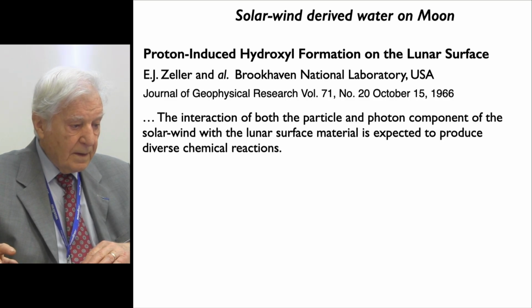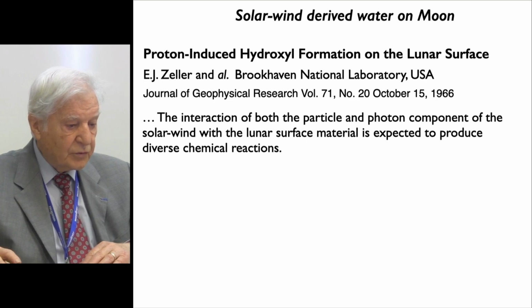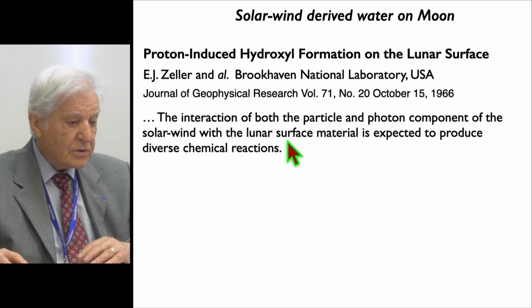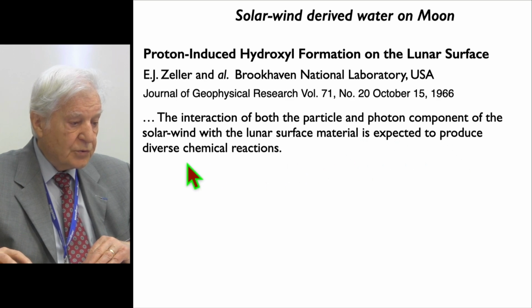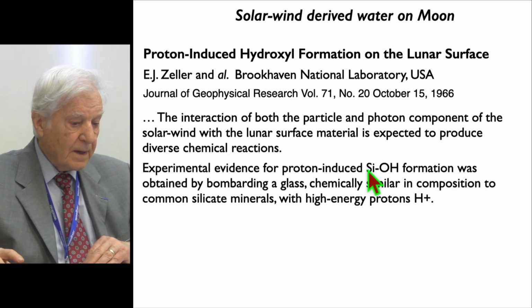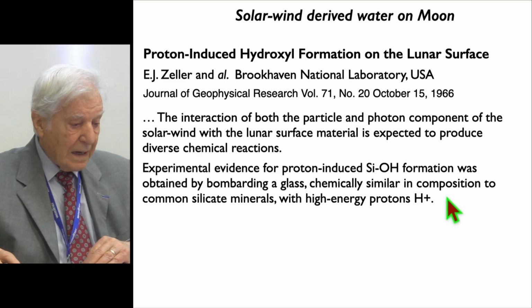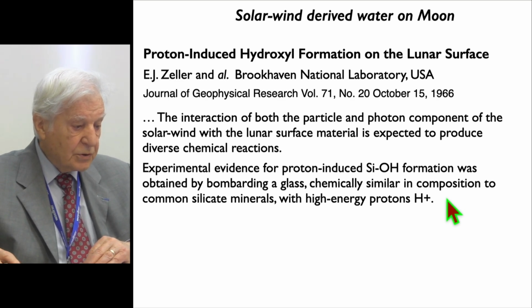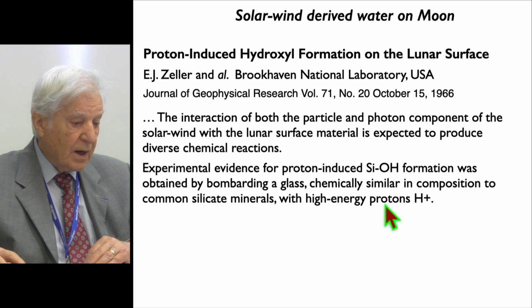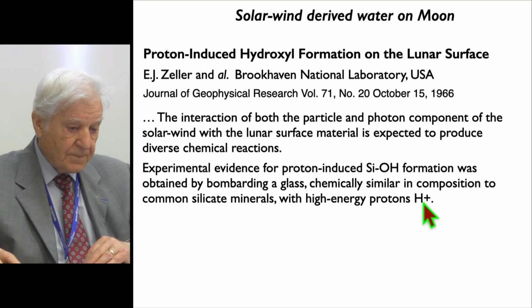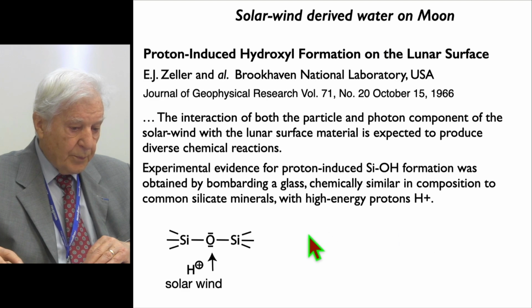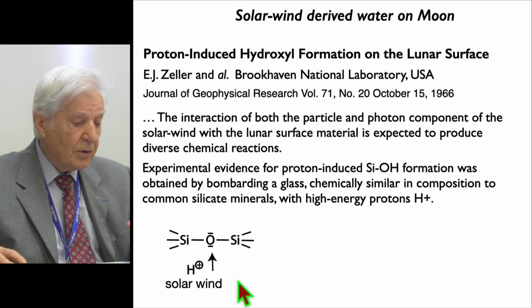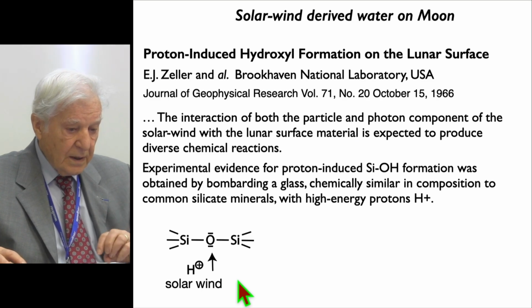I read. The interaction of both the particle and photon component of the solar wind with the lunar surface material is expected to produce diverse chemical reactions. Experimental evidence for proton-induced SiOH formation was obtained by bombarding a glass chemically similar in composition to common silicate minerals with high energy proton H+. Here we have the proton H+ from the solar wind. The solar wind contains a lot of the proton H+, which